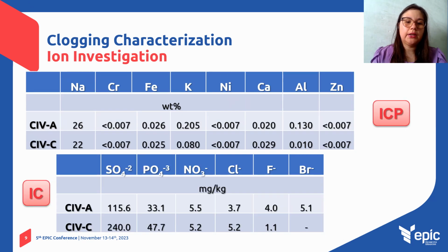Investigating the inorganic nature of the clogging materials, a significant amount of sodium was found as the cation present in their composition, detected via inductively coupled plasma analysis. Complementing this analysis, the anions that compose the clogging material were sulfate and phosphate, identified by ion chromatography, allowing us to conclude that the clogging material might have a composition of a mixture of sodium sulfate and sodium phosphate.